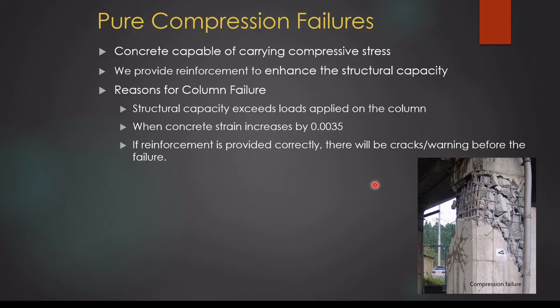We have to attend to this when doing the designs. If reinforcement stress is reached earlier, there will be warnings — there will be cracks, so we know there is an issue and we have to take action. But if, due to a higher area of reinforcement, the reinforcement does not yield but the concrete strain reaches its maximum value of 0.0035 first, then in such a situation the column could fail in brittle crushing. That is a brittle failure — if the concrete strain reaches its maximum value first, the column will fail.